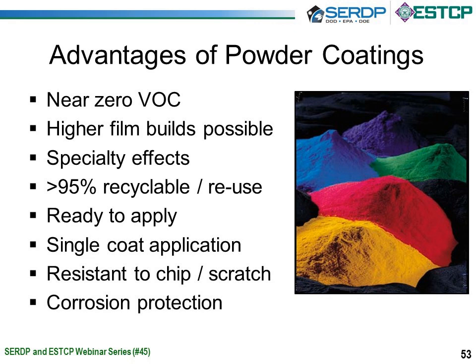So it's virtually zero, but to be absolutely correct and upfront, it's better to say near zero VOC. With powder coatings, you can get higher film builds. If you exceed the film build performance of a rheology-controlled liquid coating, you start to see sags, or you may see pops, or you'll see runs and drips. With powder coating, when's the last time you easily saw a sag or a drip coming off the part? So you can typically get higher films with a powder than you can with a liquid.